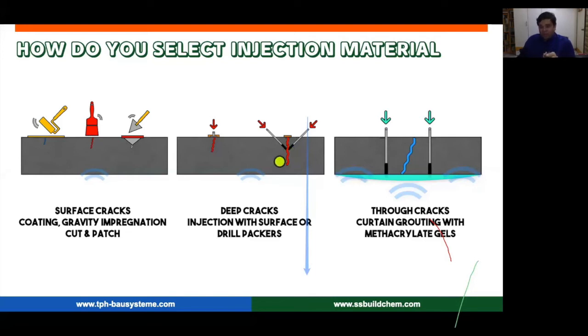Now, in certain other cases, you will find that the crack is going through and through a structural element. If this is the water side, water finds access very easily to your living space inside. In this case, you can think about going for curtain grouting. What that means is you pretty much drill through your element, through your slab or through your basement wall, and then you inject these methacrylate gels. This gel in itself forms a kind of waterproof barrier outside.